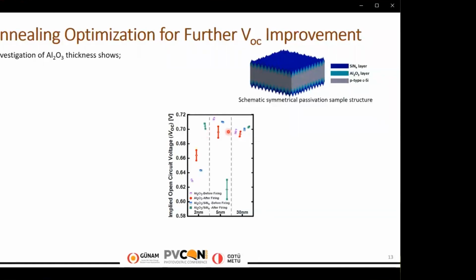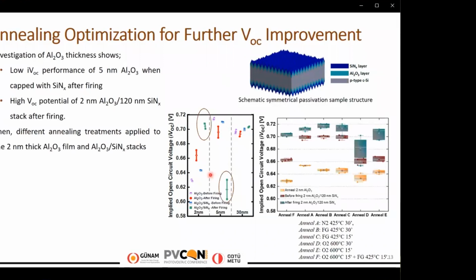On the other hand, the firing reduces the passivation quality of 5 nanometer aluminum oxide, since 5 nanometer may be thick enough to partially hinder hydrogen diffusion from silicon nitride to the interface. Since still there might be potential for the various post-deposition treatments to have different impacts depending on aluminum oxide thickness, especially regarding hydrogen diffusion.